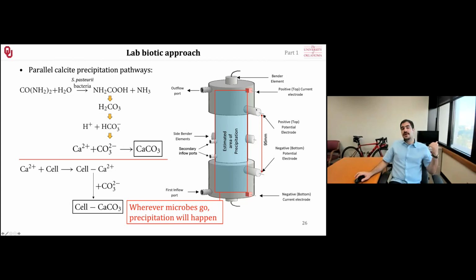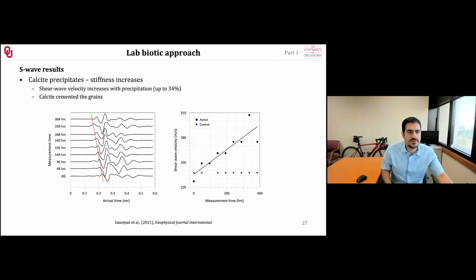So compared to the previous method, we're using the same injection ports like the previous time, but we are getting a better distribution of cementation inside our column. Or at least what we're hoping for theoretically. Let's see if we have reached that point or not. In this part of the experiment, again, we use shear wave velocity as a ground truthing method. And we were able to show that the shear wave velocity increased about 34%, slightly more, but in the same ballpark as the previous experiment.